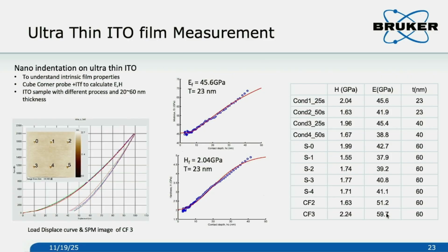This is another example. We are using our transducer to measure the ultra thin film mechanical properties. You can see this one is the 23 nanometer. It's very thin, right? So the substrate effect will probably only be 2-3 nanometer. Very difficult. So you can see if we have a very sharp tip and very well calibrated area function, we can get almost 1-digit nanometer data.